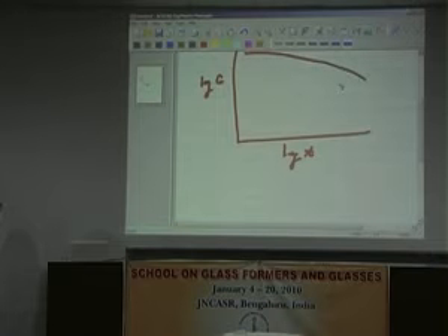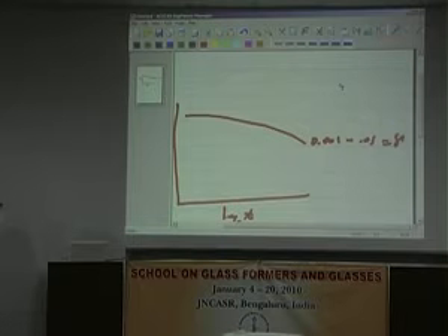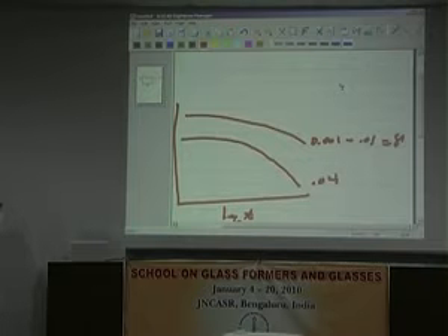Okay. Then if I'm going to plot the log of the modulus versus log time, and now at different strains. Okay, so let's say this is 0.001 to 0.01 strain. If I go to higher strains, it's going to do something like that. So this might be 0.04. And so forth, 0.08. And when my material yields, then in fact, it's just going to drop through the roof, right? Or through the basement in this case. But that's what we mean by nonlinear viscoelasticity.